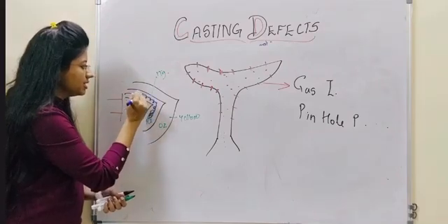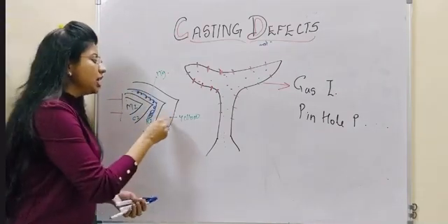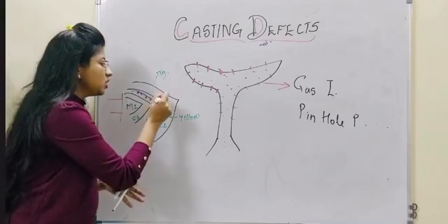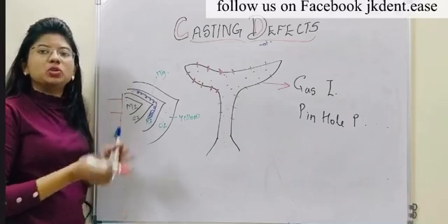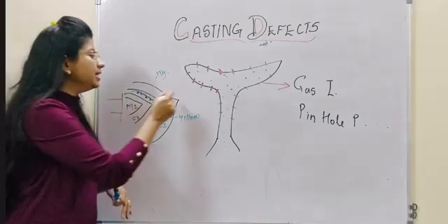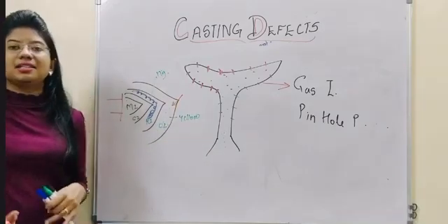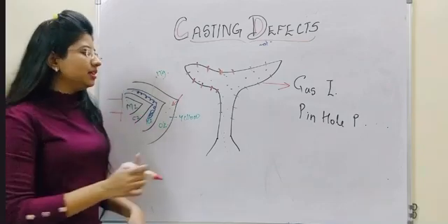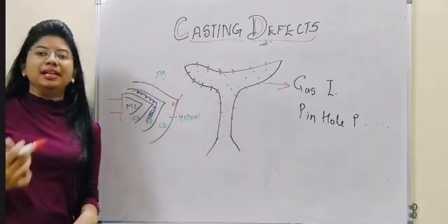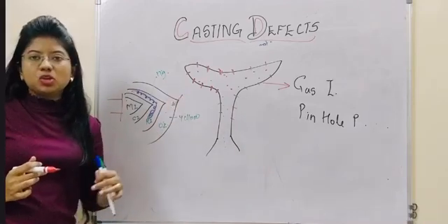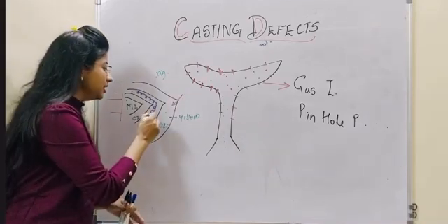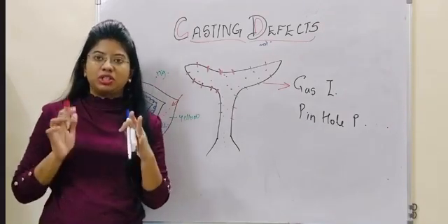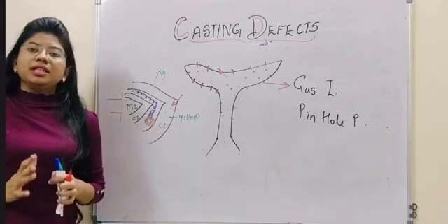So you can see that this is a blue color zone, and the yellow zone has a number of gases like oxygen, hydrogen, and it is of yellow color, and it has a lower temperature than the reducing zone. And if you are heating your casting in this zone, your casting gets entrapped with various gases like hydrogen, oxygen, sulfur, and these gases enter with the molten metal. So what you need to do to avoid gas inclusion porosity? You need to heat your casting in the reducing zone, that is the blue flame of the gas torch. So in this way, this porosity can be avoided.